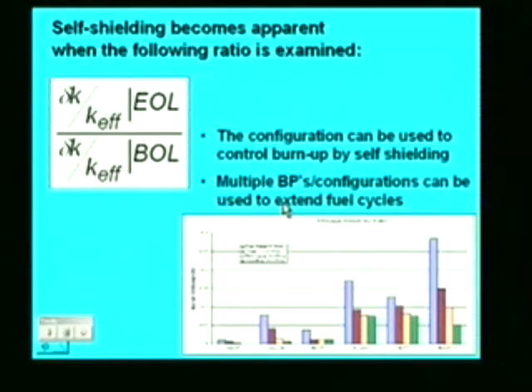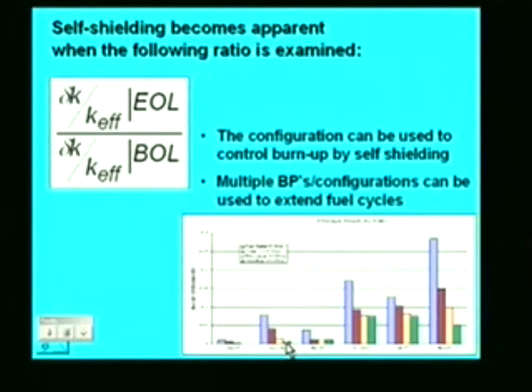The self-shielding effect becomes apparent if we look at a simpler ratio. If we look at just the negative reactivity due to the burnable poison at end of life over beginning of life, in other words, how well does it burn up, we notice gadolinium does quite well. But let's pick any one of them, and we notice kind of what we expect. If it's homogeneous, it doesn't completely burn up, but if we spread it into a thinner coating and we have less self-shielding, it does. And if we put the burnable poison out in a clad, we go out into a region where the thermal flux is higher, so we don't have the thermal flux depression of the fuel, it will burn up even more. So just the configuration will give us another parameter to adjust the burnable poison.